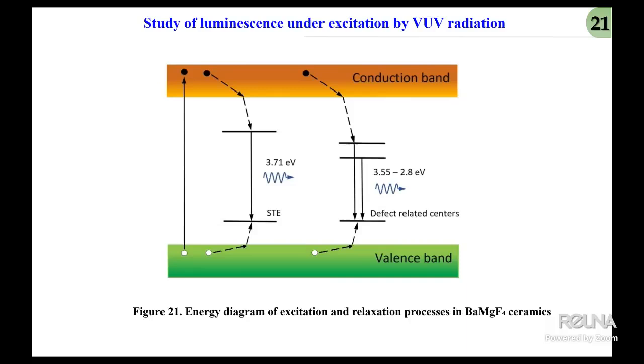This scheme clearly demonstrates that luminescence in our ceramics under VUV excitation is formed as a result of the interplay between interband transition, exciton relaxation, and defect-related channels, which is fully consistent with the experimental excitation and emission spectra.